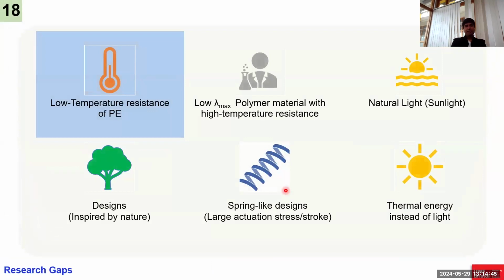So moving forward, based on our research work, we found that polyethylene does not have a very high melting temperature. So there is a term used, alpha relaxation temperature. We see that if we increase the concentration of BZT, there will be an increase in the actuation stress. One might wonder why we cannot go further than 5% of BZT.